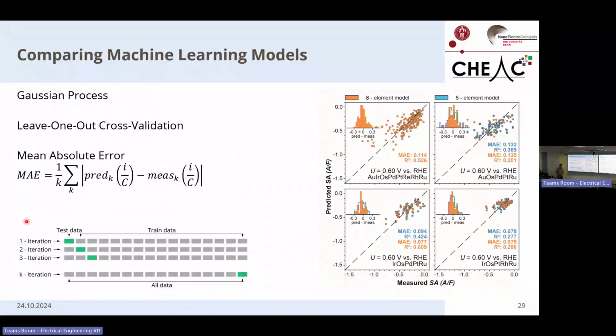So now as I have a data set composed of different compositions and their associated activities, I can go on and train different models. And now we need to find a way to also evaluate the performance of these trained models. And for this, we use the so-called cross-validation methods. In the cross-validation method, you take your entire data set and you split it into a test set and a training set. This training set you then use to fit a Gaussian process, and then you predict the values for these test data points. And by taking the difference between the prediction and the true value, you can get an overview of how well the Gaussian process predicts unseen values. So the mean absolute errors that you see over here are a reflection of how well a Gaussian process predicts unseen values instead of how it fits seen values.